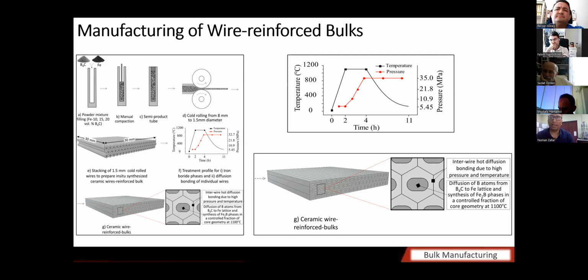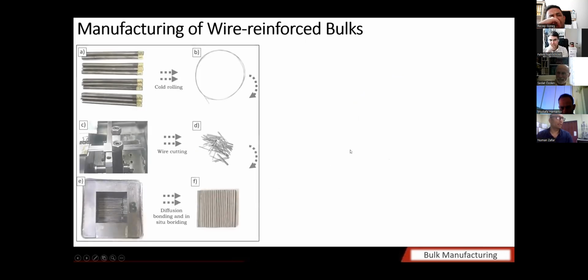Exactly. You explained it better than I do, because eventually the boron diffusion will stop after a certain number of micrometers from the surface of the steel. If you want to proceed to more iron boride phases, you have to use an in situ approach. And the pressure is also increased eventually, and it reaches 35 megapascal. But why 35 megapascal? Here is the state of wires at different manufacturing levels.